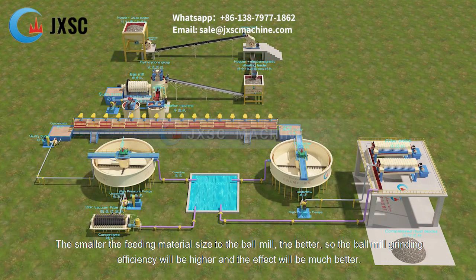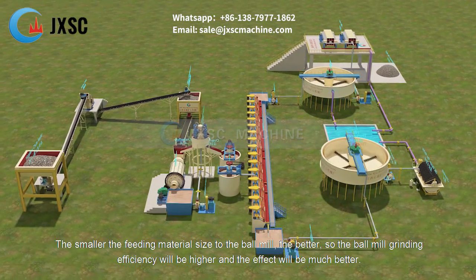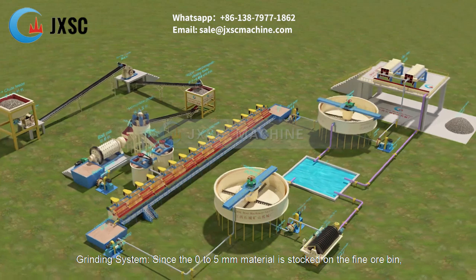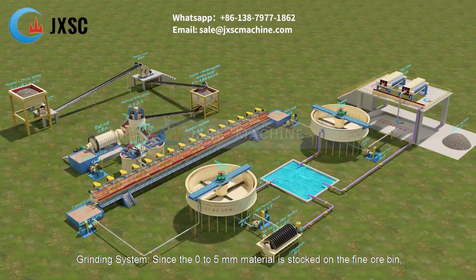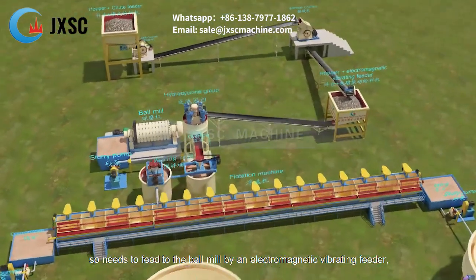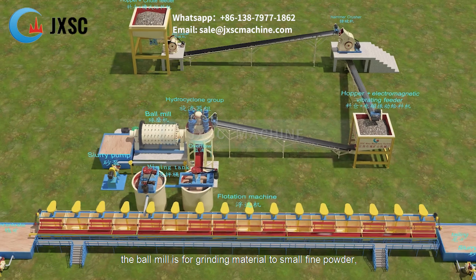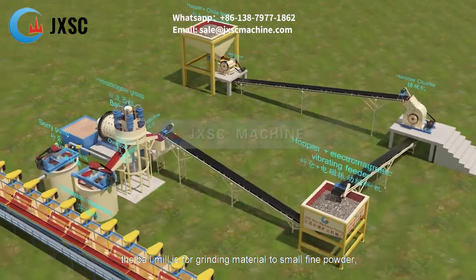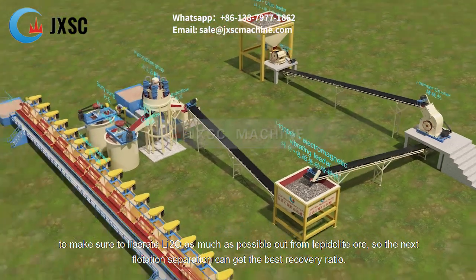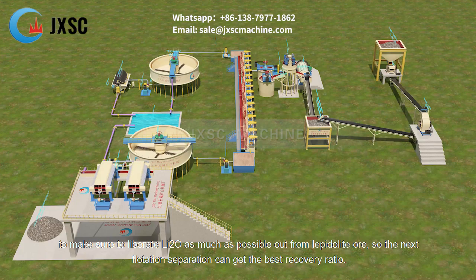The smaller the feeding material size to the ball mill, the better, so the ball mill grinding efficiency will be higher and the effect will be much better. Grinding system. Since the 0 to 5 mm material is stocked in the fine ore bin, it needs to be fed to the ball mill by an electromagnetic vibrating feeder. The ball mill is for grinding material to small fine powder, to make sure to liberate Li2O as much as possible out from lepidolite ore, so the next flotation separation can get the best recovery ratio.